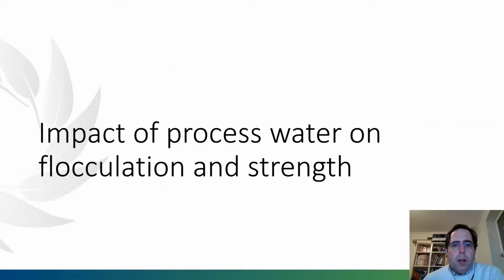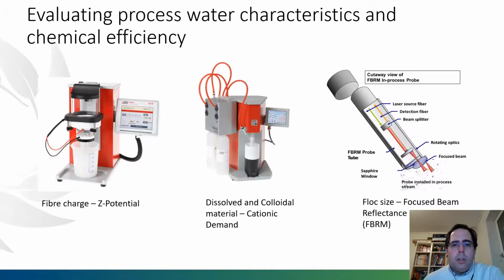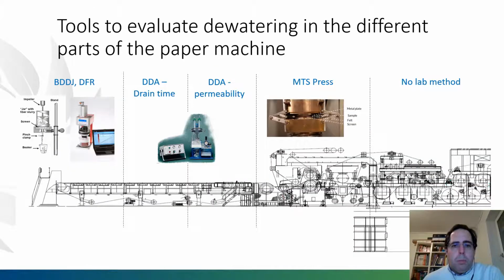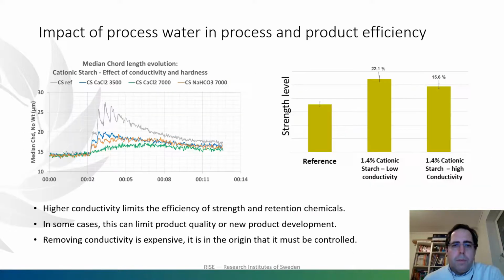So if we go a bit deeper into how this process water is linked to the strength and to the flocculation, what we have been doing, so using, we could say, quite traditional systems, but also we have added the focused beam reflectance measurement, which will give us an idea and a way to follow the size of the flocs and therefore be able to optimize. When it comes to simulating the paper machine at lab scale, we have used different tools depending on what we want to improve, because it's very important that when we try to optimize the dewatering, we are considering what is happening in the different parts of the process.